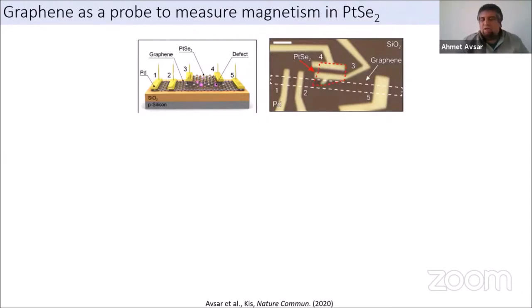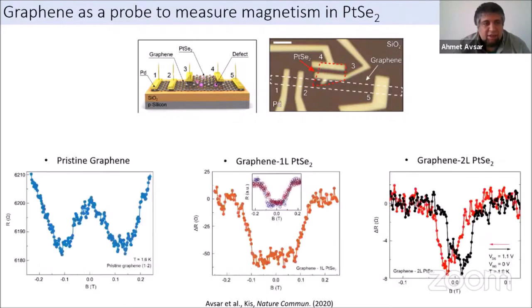And recently we have also studied the monolayer and bilayer PtSe2, and we were curious if the magnetic ordering persists down to the monolayer. But again, measuring these devices with transport at the monolayer limit is very challenging because they are extremely resistive. So what we did is we put graphene on top, and then we use graphene as a probe, as a sensor to sense the magnetic response of the substrate. And what we do see is, if you don't have any PtSe2 under the graphene, you do have a weak localization response, which is typical for graphene. Okay, and if you have one layer of PtSe2 and two layers of PtSe2, we do have again different types of magnetic ordering which can be probed through the graphene.